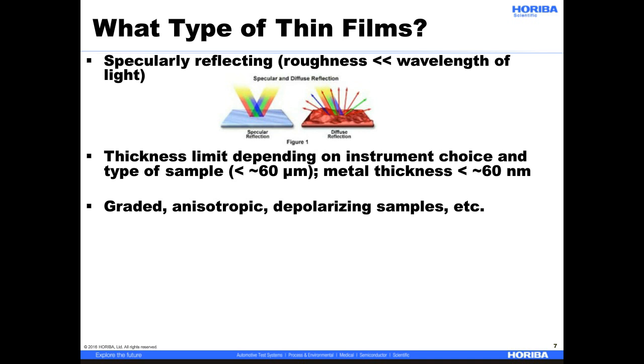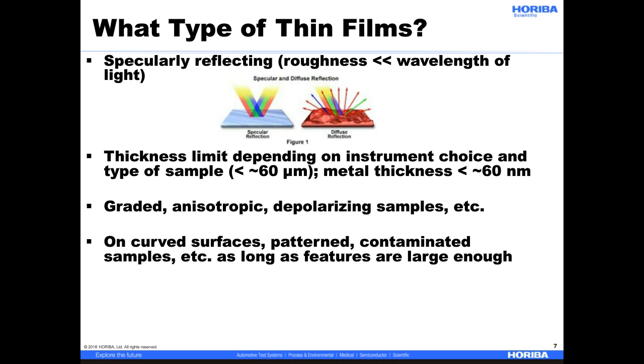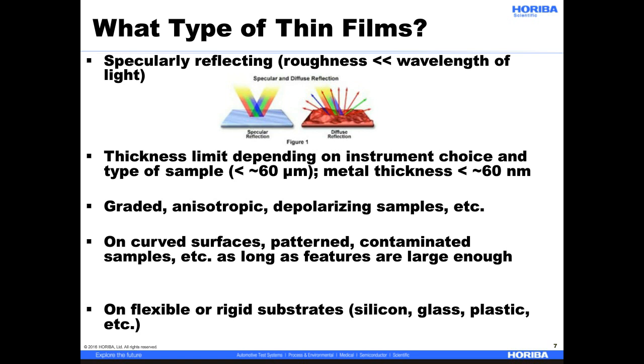These can be graded, anisotropic, depolarizing samples. And we can do ellipsometry measurements on curved surfaces, patterned surfaces, contaminated samples, as long as the features are large enough such that the beam of light is over the entire feature. This can be on flexible or rigid substrates, such as silicon, glass, plastic, etc., and on substrates no larger than about 50 millimeters thick. Again, this depends on the Z height capability of the stage that you're using in your ellipsometer.